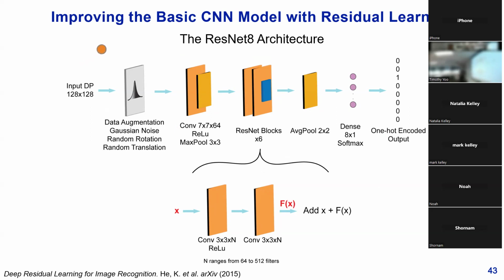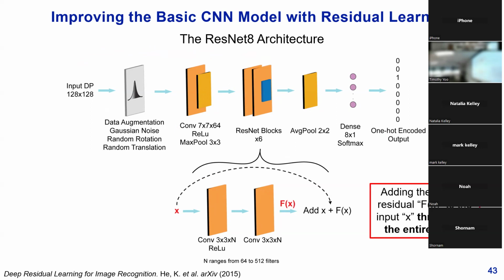And so the overall model, at least the shell of it, is pretty much the same. You have your data augmentation layer going through an initial convolutional filter, but what's really important here are these residual learning blocks. What's going on in these residual learning blocks is that you have two convolutional filters, but what's really significant here is this adding step that happens at the end that adds your original input to your output. The original authors of this model hypothesized that by doing so, it would encourage the model to learn the perturbations or the residuals of the input data it's being trained on, rather than trying to fit the complex mapping individually for every piece of data produced by the convolutional filters. And so that's what we're going to go with here.